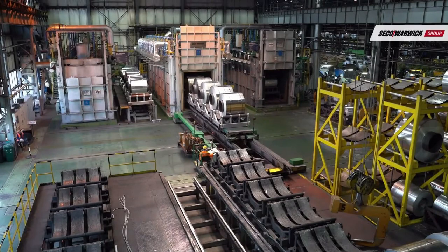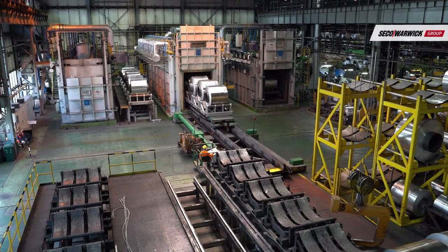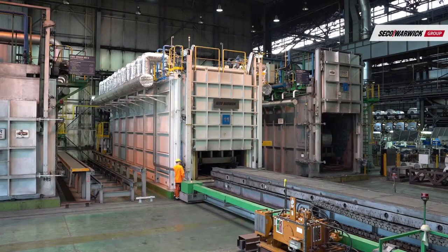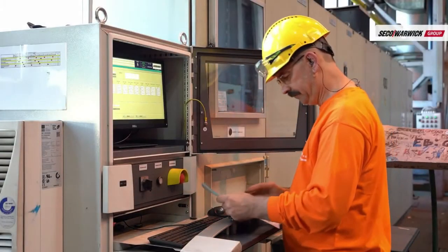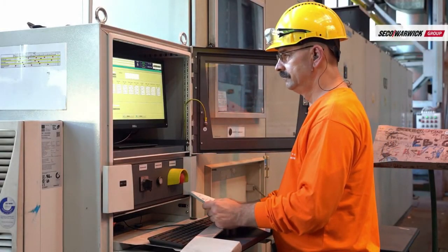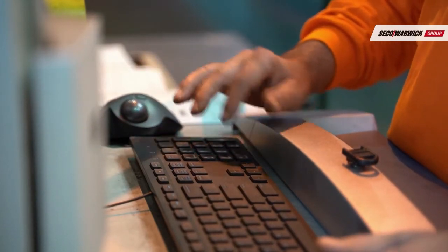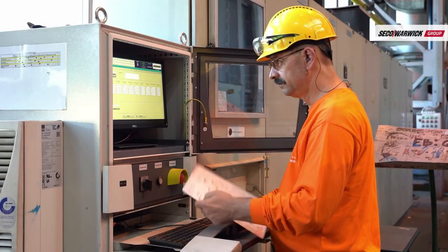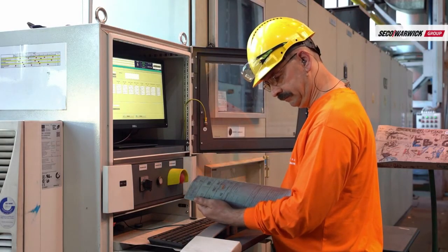The mathematical model as an online controller, in cooperation with the primary system of the furnace, simulates the current temperature field in the cross-section of the coil using information on the current conditions in the furnace's heating chamber and the parameters of the heated coil. SICOIL allows you to choose the location of the so-called virtual control thermocouples, the indications of which can be used to control and regulate the process.